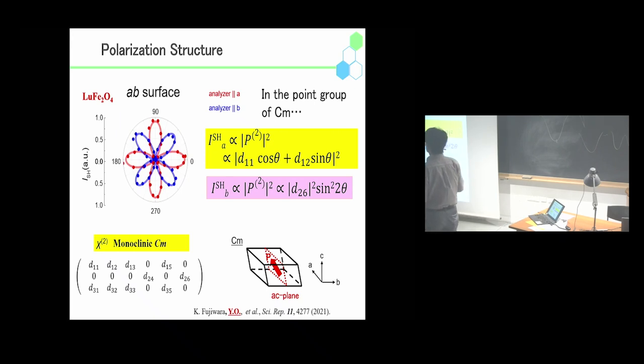By using these tensor components, the SHG polarized along the A-axis is described by this one, and SHG polarized along the B-axis is described by this one. By using these formulas, this angle profile is well fit. So we succeeded in concluding that the polarization structure of this material is Cm, in which the polarization exists in the AC plane. This is the first conclusion.